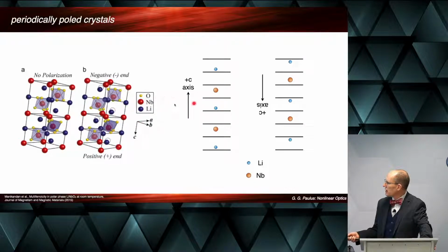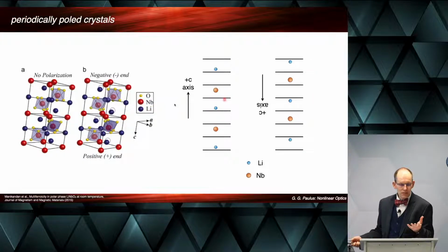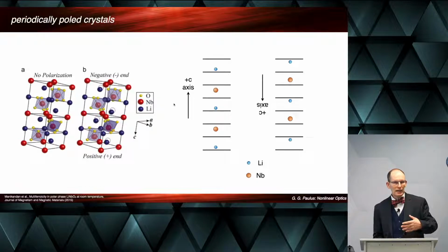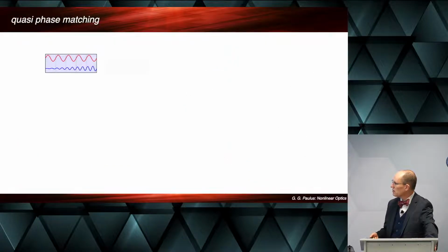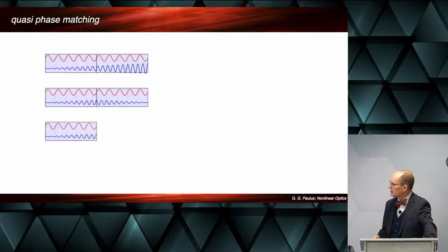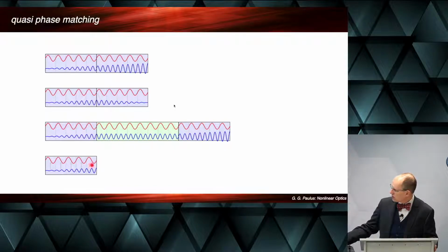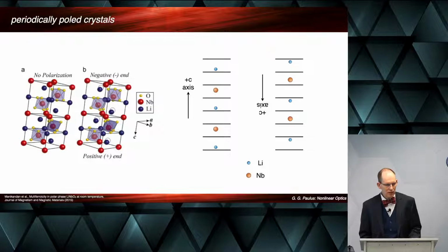The interesting thing is that for every dipole there's a direction. And so by turning this crystal around, you can invert this dipole moment, and therefore you would also change the phase with which you create the second harmonic. And with this, I go back to this slide here. If you look carefully, you see arrows indicating the direction of the electric dipole moments, and you would just put another crystal here where the direction of these arrows is inverted. A little bit hard to see, but this is the idea.